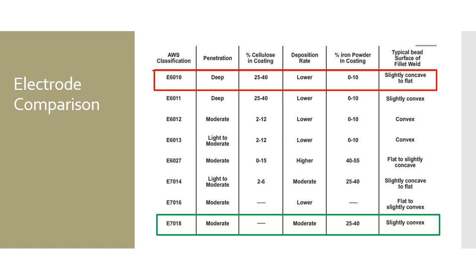7018 has a moderate deposition rate, and it's known as a fill freeze. It kind of freezes quick, but it isn't a fast freeze like 6010. 6010 can have up to 10% iron powder in the coating, whereas 7018 can have up to 40%. So this contributes to our deposition rate. We've got our electrode core, which is basically a piece of wire, and around it is this electrode flux coating. Well, with 7018, they decided they needed faster deposition rates. So in that flux coating, they threw in iron powder, and it helps you get a faster deposition rate for this electrode. And then you'll see the typical bead surface of a fillet weld.